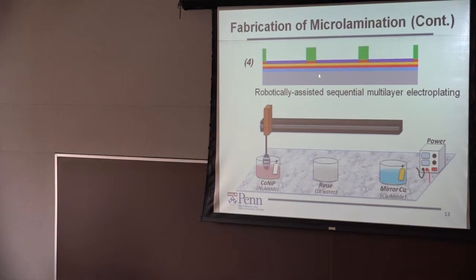And so first of all, you have one layer of cobalt nickel phosphorus plated, and to avoid contamination, you have this rinse bath over here. And then you grow another layer of copper. Right? It's simple, A, B, A, B, A, B.